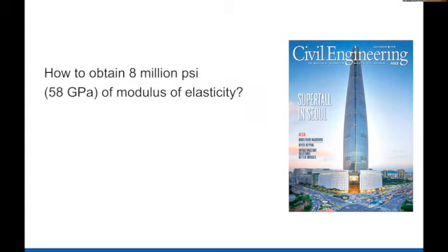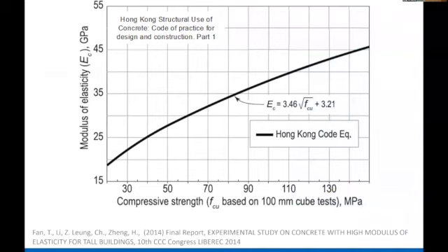So for good design of super tall or tall buildings, they want a modulus close to 60 gigapascal, or 8 million PSI. Currently, we have about 4. So how do we double it? Well, the only way being done now is increasing the strength. This is a classical plot of modulus of elasticity versus compressive strength. This is, for example, the Hong Kong code, similar to the ACI code.